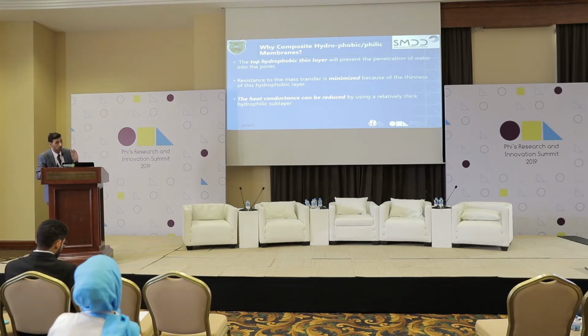We believed that this design will revolutionize the membrane distillation process, because the top hydrophobic layer, which is very thin, will prevent the penetration of the liquid water through the membrane. On the other hand, the resistance to mass transfer is minimum because this layer is very thin. The heat conductance can be reduced by the hydrophilic layer because both hydrophilic and hydrophobic contribute to the heat transfer, while only hydrophobic contributes to the mass transfer.